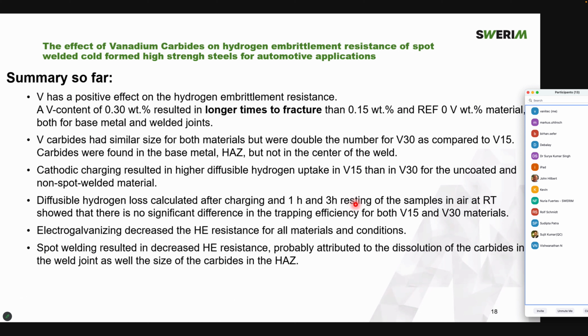When we did cathodic charging on the materials, we saw higher diffusible hydrogen uptake in the 0.15% material than in the 0.30%. And that's both for the uncoated and the non-spot welded material.